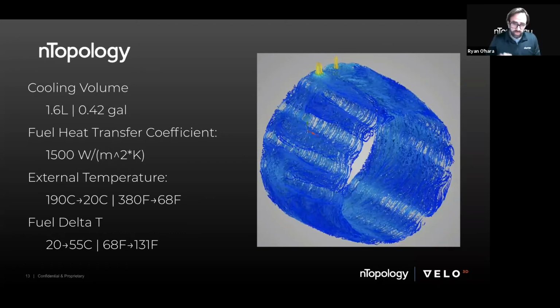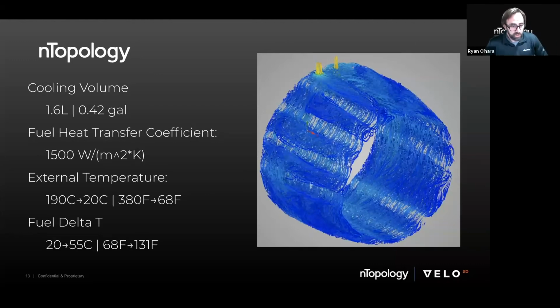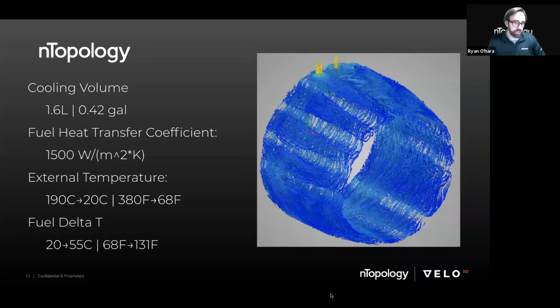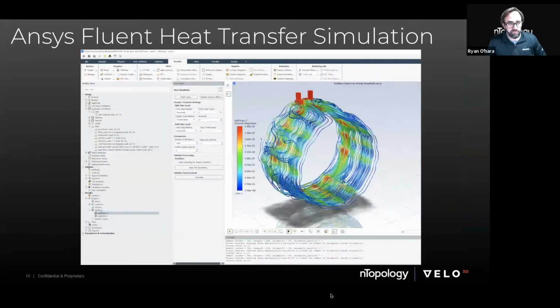Fundamentally though, what we did is we took the external temperature from being about 190 C or 380 degrees Fahrenheit. So basically really hot, right? Like creating an oven there. And then with the fuel, we were able to cool the exterior of the case down to about standard temperature and pressure, which is where the fuel is in its storage tank. And fundamentally, we're also heating the fuel, right? And I think Enrique can talk to this a little bit more in detail later. But the idea is that by transferring that energy, we're conserving that energy, and we're basically preheating the fuel so that it's going to combust more efficiently. So kind of a win all around.